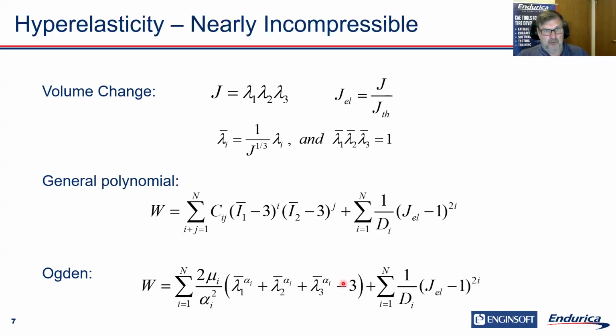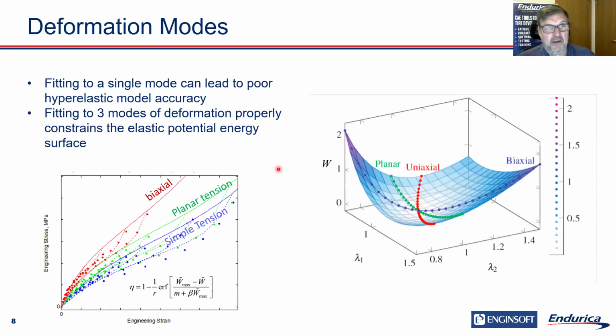In Endurica, we often use an Ogden model, which is written not in terms of the strain invariants, but in terms of the stretch ratios lambda. So if we think about characterizing this function W with respect to two variables, here we're doing it with respect to two stretch ratios, you get some type of response surface for W. If you just do one experiment, you'll just have one line on this response surface and you won't know what the rest of the surface looks like. So it's good to do experiments in different modes of deformation.